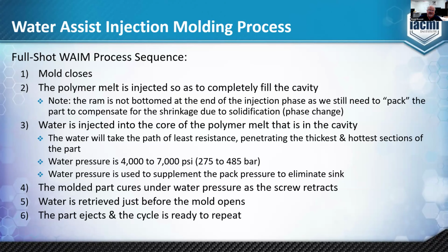The water pressure is used to supplement the pack pressure to eliminate sink on the surface of the part. The part cures under water pressure as the screw retracts. The water is relieved just before the mold opens, the part ejects, and the cycle is ready to repeat.